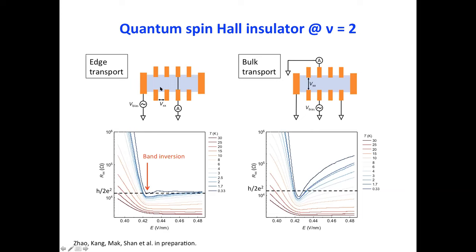Yes. And the channel length here is about a micron to 2 microns. It's already pretty long, right? It turns out that this is good because the channel is purely defined by the gate, so it's a very smooth edge. It doesn't really have any atomic-scale roughness around the edge. So I think that's the main reason the quantization is pretty good.